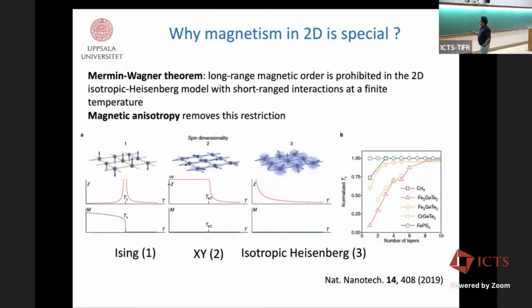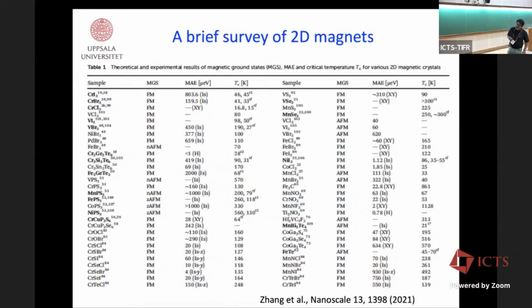If you look into this plot, you will see that several two-dimensional magnets are listed here. The normalized TC as a function of the number of layers: even in the monolayer regime, you see non-zero values. Chromium iodide (CrI3) is one of the first ones, a ferromagnetic insulator, a very interesting system, but its Curie temperature is rather low, around 45 Kelvin in the monolayer regime. So not of much use so far, but I will talk about some metallic ferromagnets, the iron germanium telluride class, which has a very high Curie temperature.